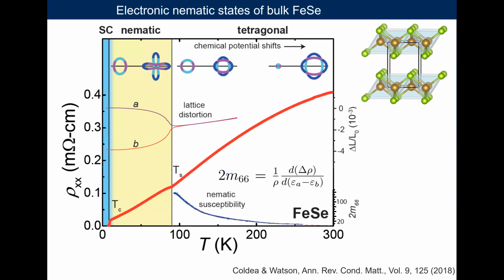In the tetragonal phase, the standard method to establish that the system has nematic behavior is measurements of its nematic susceptibility. What that means is we take a material, place it on a piezo stack, and apply a small amount of strain to it along the direction which will break the symmetry. And we measure the elastoresistivity response, in particular the m66 parameter, and that represents the nematic susceptibility of the system, and it has Curie-Weiss-like behavior. So this is equivalent to what we often do for a magnetic system when we measure magnetic susceptibility. In a nematic system, we measure the nematic susceptibility via a small amount of strain. And another signature, obviously, is that the system will have the transition from tetragonal to orthorhombic, with a small distortion of its lattice as well.